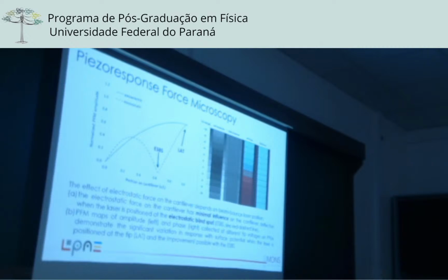And the problem for the moment is, if you are measuring the properties correctly, you are 1 order or even 2 orders less than what was published. And it is really a nightmare to show and to prove that what we are measuring is the actual value, and not a value measured non-intentionally by people who didn't know about the artifacts. They say we have a coefficient of 300, and you are measuring, for instance, 30, and the actual value is maybe 40. It's extremely complicated to measure PFM, but it's doable.